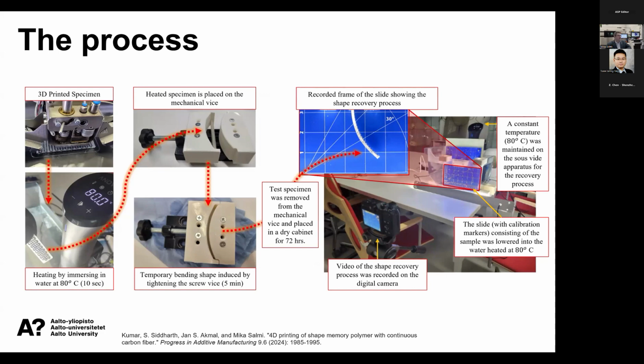So when it's in the soft state at 80 degrees, we change the shape and let it cool down. Then it will keep that shape. We bend it slightly, but not too much, so that nothing really starts breaking there, because then we don't know what we are measuring. Then we dried those samples, and put them in hot water and recorded the shape recovery process.